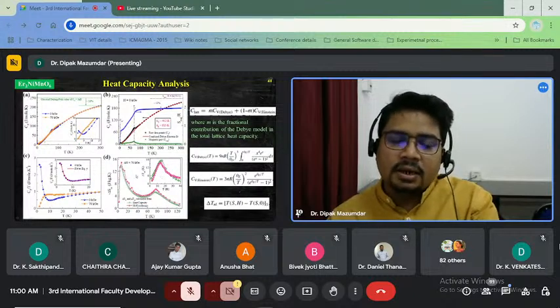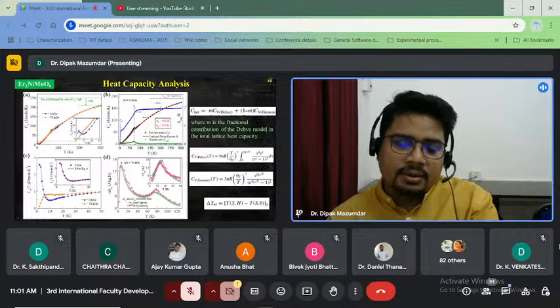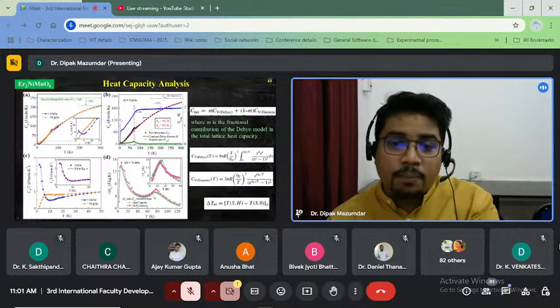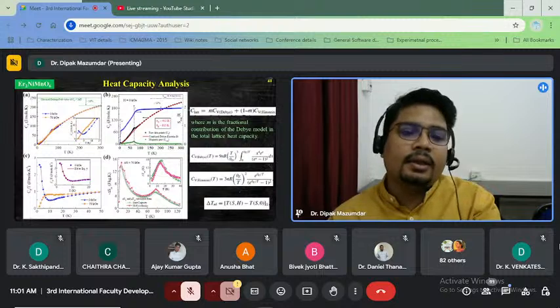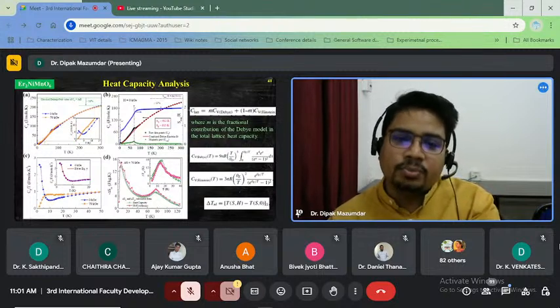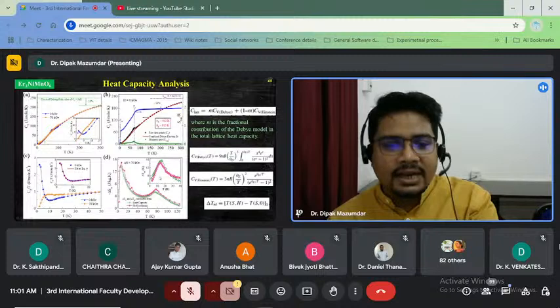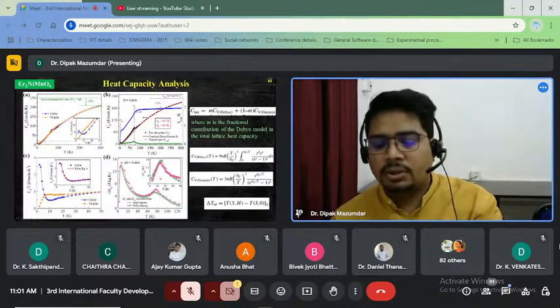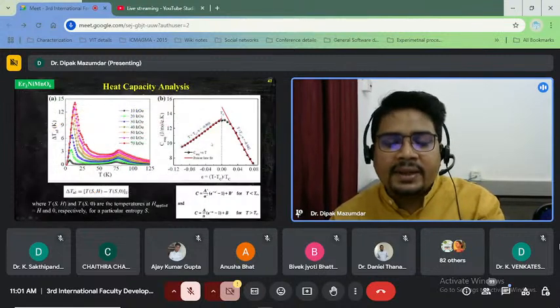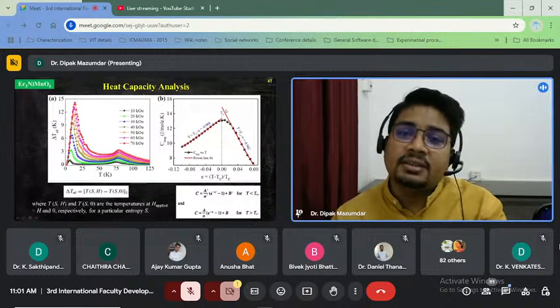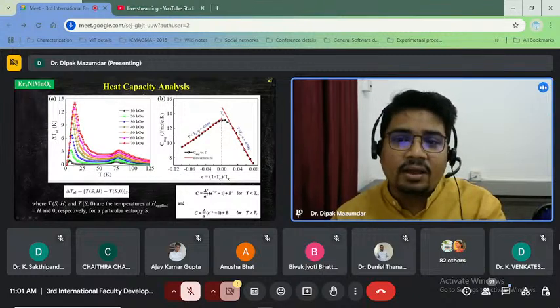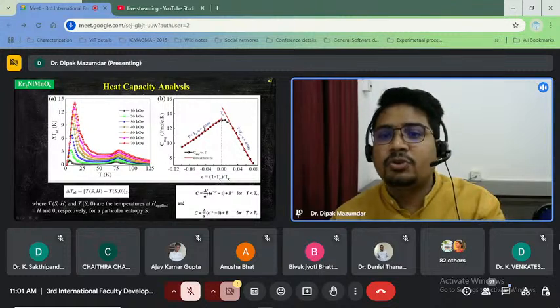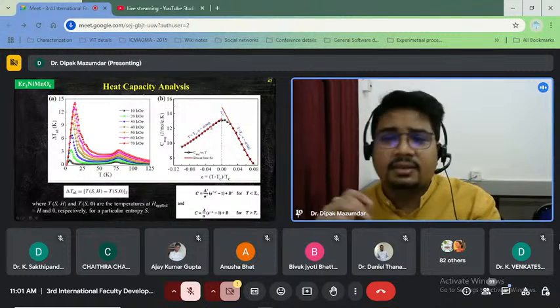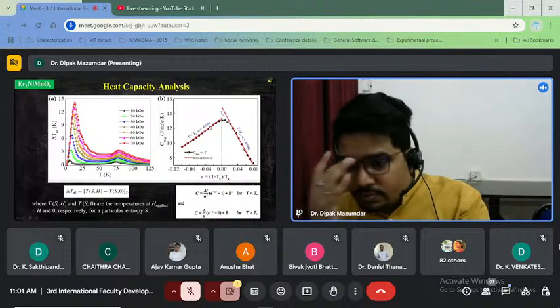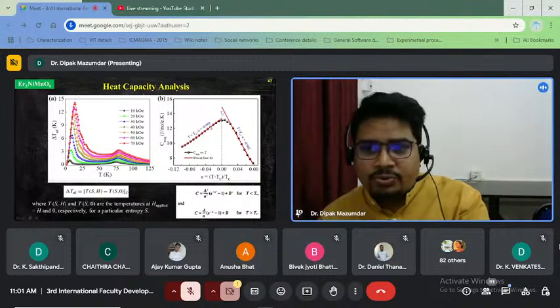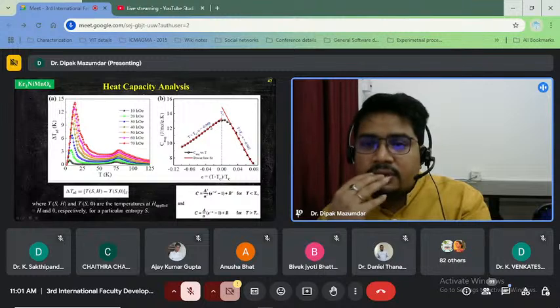So you can see in this picture the magnetic entropy change obtained from heat capacity data and isothermal magnetization almost match with each other. Similar for delta adiabatic temperature also. And from this heat capacity data, we can also estimate the third critical exponent, which is known as alpha. The value of alpha is 0.96, which is very, very high. Its value should always be less than 0.1. So why will this happen?